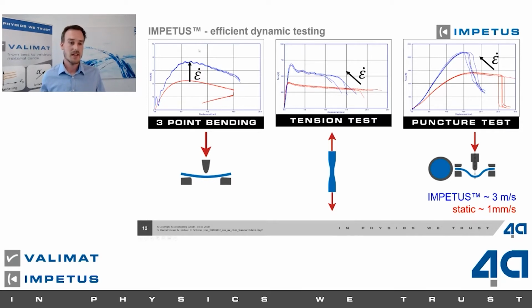You can directly see out of the measurement results the big influence of the velocity, or the strain rate, I will say. So we are not just raising the force level, as you can see here in the bending. We also got a stiffer response in the stiffness over the velocity. This is the viscoelasticity and the viscoplasticity here in the force level. And not only the deformation behavior changes over the strain rate, also the failure changes with the strain rate. So we got an earlier failure at higher strain rates. And this all you can see directly out of the measurement results.